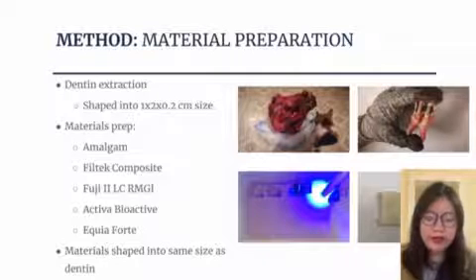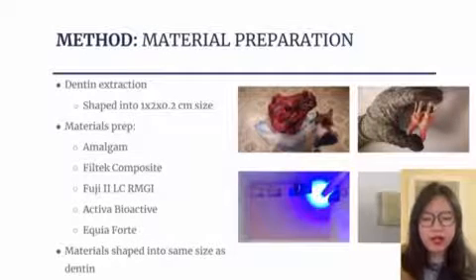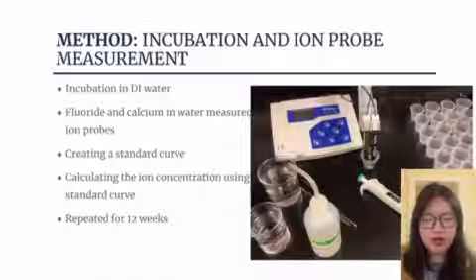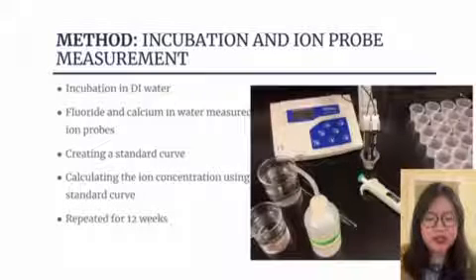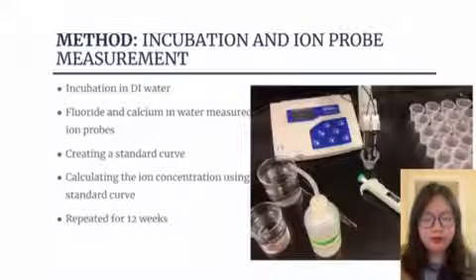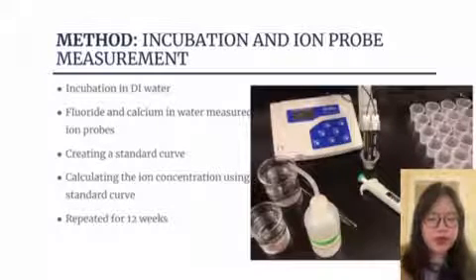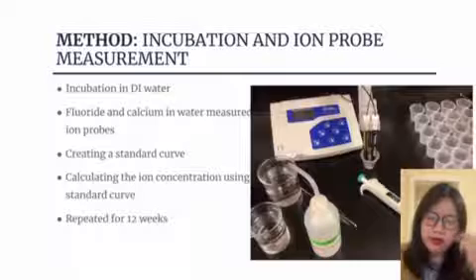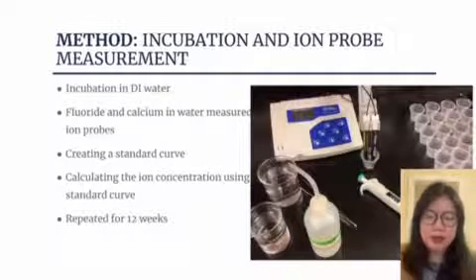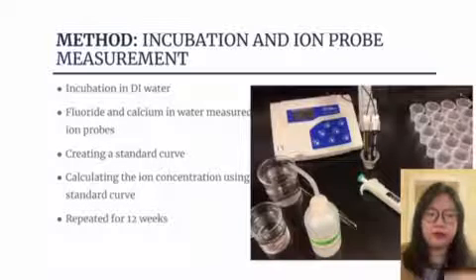After successfully shaping the material, I incubated all of them in DI water. The materials were incubated for a week, after which the water was changed, and the fluoride and calcium levels in the extracted water were measured using calcium and fluoride probes. I created a standard curve to get the actual value of calcium and fluoride concentration. This process was repeated for 12 weeks to get a sense of how many ions they are releasing over a long course.